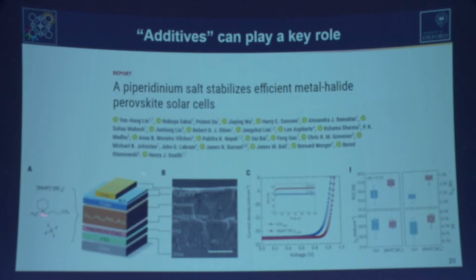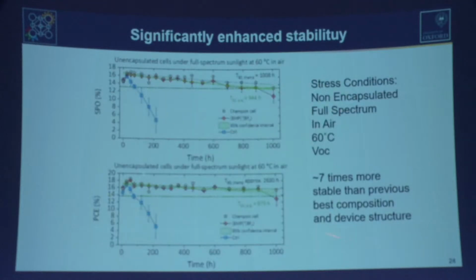This is an example of a piperidinium salt that was added into a perovskite layer, some work that we did. When we add this material at just 0.3% with respect to the main perovskite material, a relatively low concentration, we get a nice improvement in efficiency, in voltage of the solar cell, and importantly, a big improvement in stability. So these additives suppress some of the degradation processes that can happen in these devices.